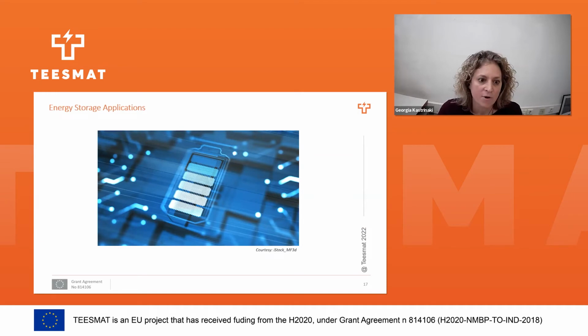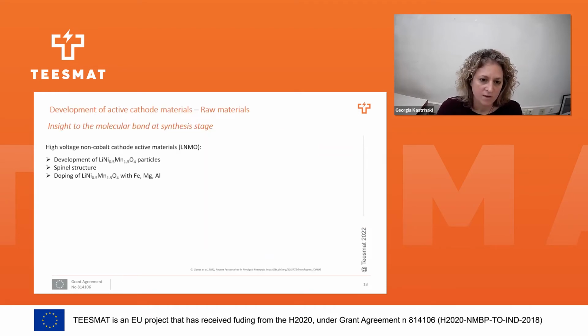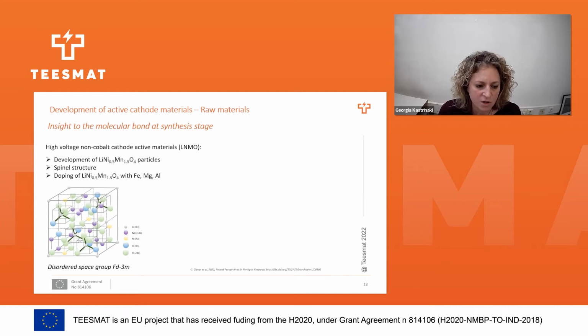Now, an example from energy storage applications. We tried to develop an active cathode material, literally from a non-cobalt active material. It was from the LNMO family. It follows a spinel structure, and we tried to dope it with iron, magnesium, and aluminum in order to see different kinds of effects on its capacity and different aging and cycling. So literally, this is the structure that this spinel follows. Through calcination, we can manage to have the disordered phase, which is this Fd3m. And here you can see the different lithium, manganese, and nickel ions and how they are formed in the lattice structure.